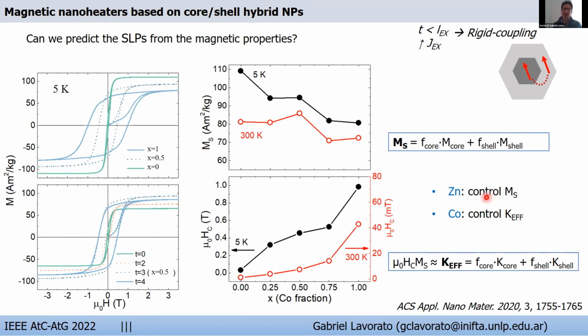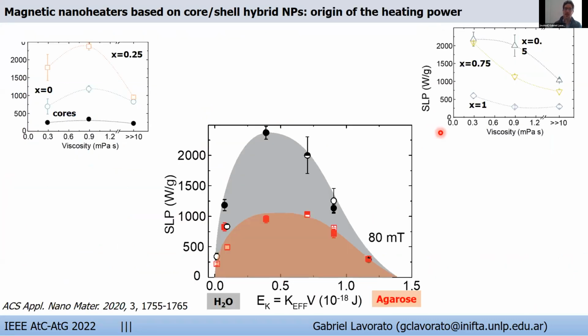This calculation is in good agreement with the core and shell fractions obtained from electron microscopy and with the reference anisotropies of each phase, and confirms the role of zinc and cobalt in the modulation of the magnetization and anisotropy of the system. So finally, we built a graph of the heating power as a function of the overall anisotropy energy, which takes into account the effects of both the effective anisotropy and the size of the nanoparticles. By doing so, the heating power of the whole set of samples can be shown in a single diagram. Here, the red one is for a medium with large viscosity, and the gray one is in water. So 2 different responses are clearly observed.